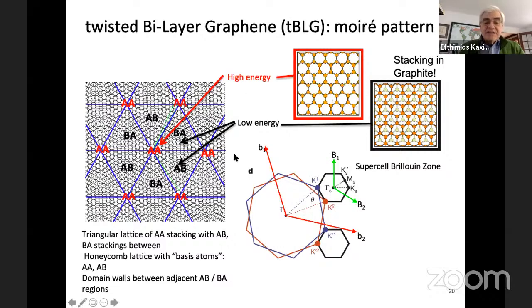Or alternatively, in other regions, which are called AB or BA, the top layer, again in orange, obscures only half of the second layer, shown now in yellow. So you see only half of the atoms of the second layer. And this is called an AB or BA stacking. The two lattices don't exactly obscure each other, but partially hide each other. It turns out that if you try to arrange two layers of graphene, AA is a high energy situation. The atoms don't like to be in this situation. They like to be in these low energy situations, which correspond to the AB or BA stackings. So this is the real space arrangement.